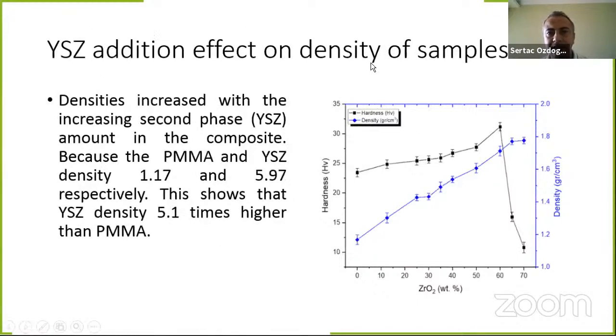And we can see here the density of the samples. Densities increased with addition of powders because polymethyl methacrylate and yttrium zirconia densities are 1.17 and 5.97 respectively. This shows that density is 5.1 times higher than polymethyl methacrylate.